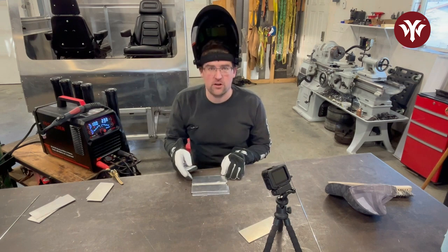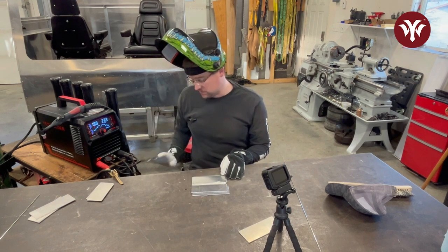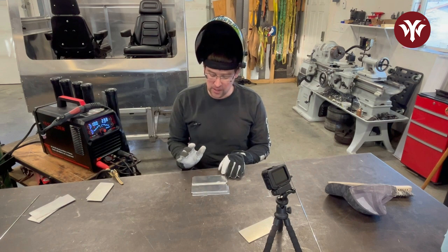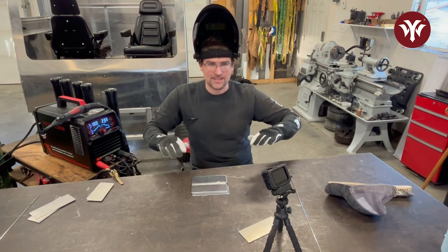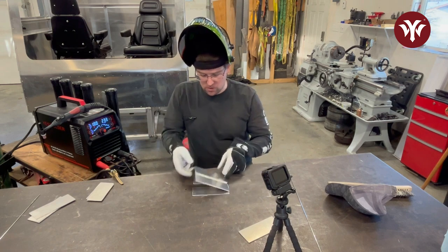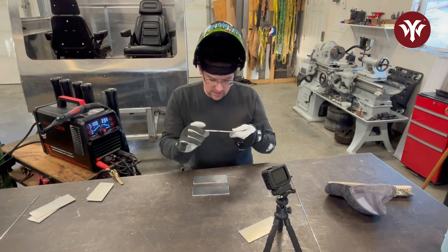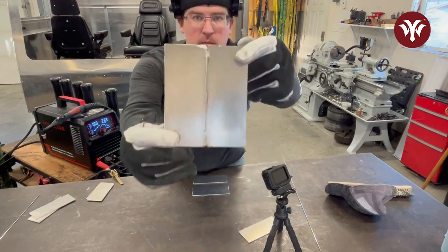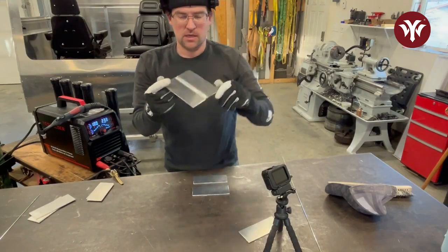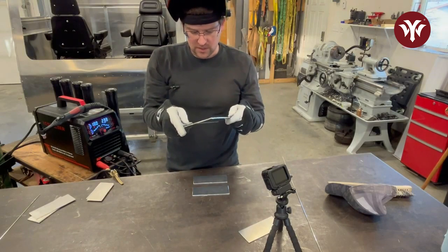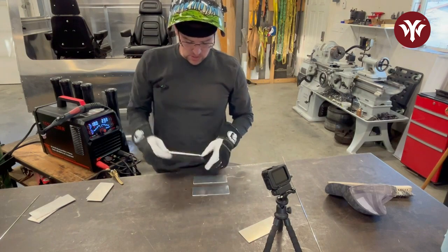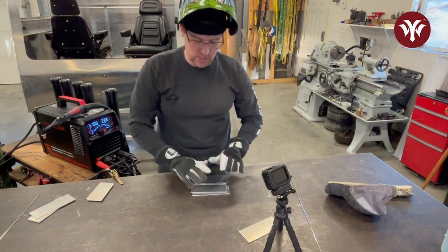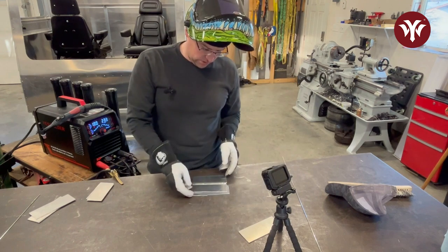All right, so first thing I already noticed from that, I felt like I was getting approximately the same amount of current, but the weld flattened down, which means it was sinking in more, penetrating a bit more. And I'll show you here, it's really hot, but you could see I was starting to see that penetration come through the backside. So again, that shows you that's something you gotta pay attention to. You gotta pay attention to the material you're welding on and how much heat it's pulling away from your part.